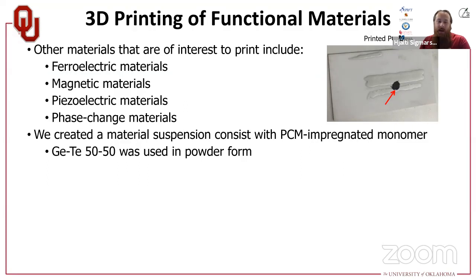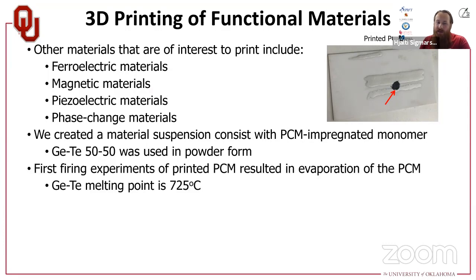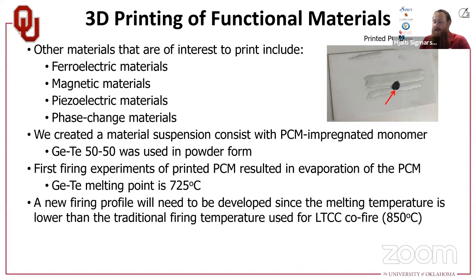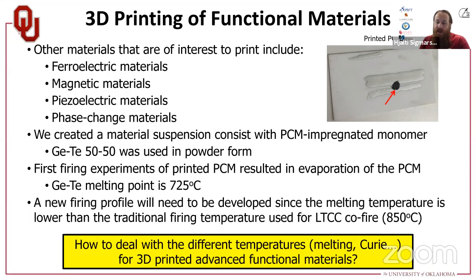Anyway, so we took the GeTe 5050, which is good for getting low loss, and we put that into a monomer as well, and we tried to print that. However, we failed to take into account that GeTe actually melts at 725 degrees Celsius, and the LTCC process is about 850, so we ended up evaporating all of our GeTe. But still, it's something that we want to be looking at.